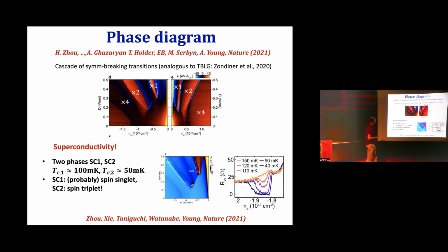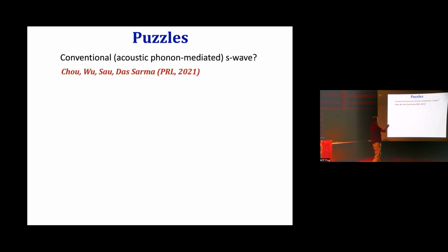That, of course, is not enough. Okay, so we'd like to know what is the mechanism of superconductivity and what's the nature of superconductivity in this material. And there's an argument which I really appreciate. I think it's an argument not to be taken lightly, which is basically promoted in this paper. I won't talk about the details, but the gist of the argument is that 99.7% of the superconductors in the universe are totally conventional, phonon mediated. Find a new superconductor, it's very likely to be one of those. So it's basically a conventional phonon-mediated superconductor unless proven otherwise. That's really not a stupid argument.